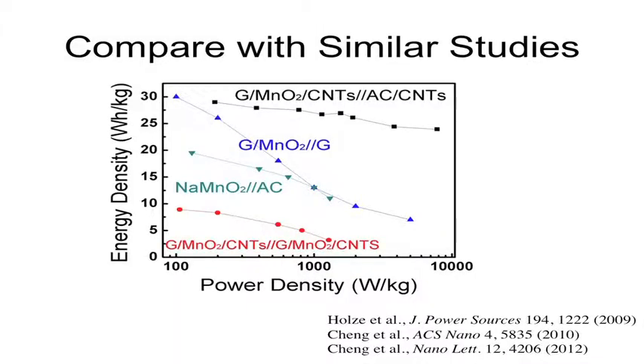And if you look at the performance of the supercapacitor that we are making, normally what other people do in a similar system is that whenever they increase the charging speed, meaning they increase the power density of the system, their energy density drops very, very quickly due to the low conductivity of the material. But with this really good composite that contains graphene, carbon nanotube, and metal oxide, we do still drop from 30 to 25, but it's not dropping that fast.